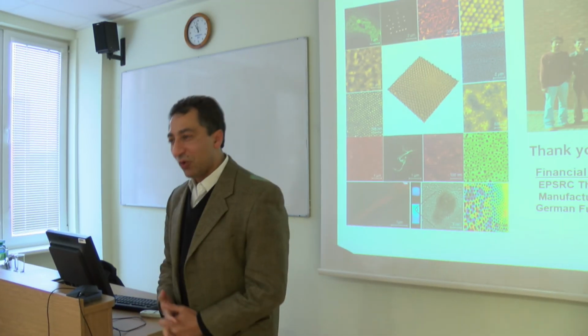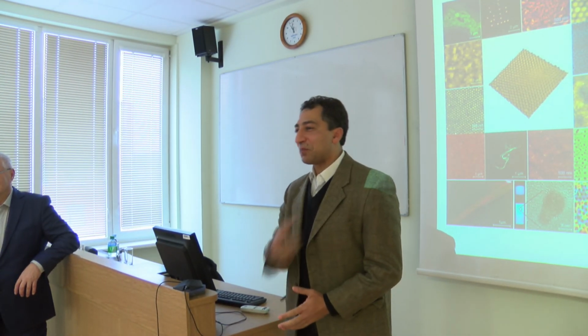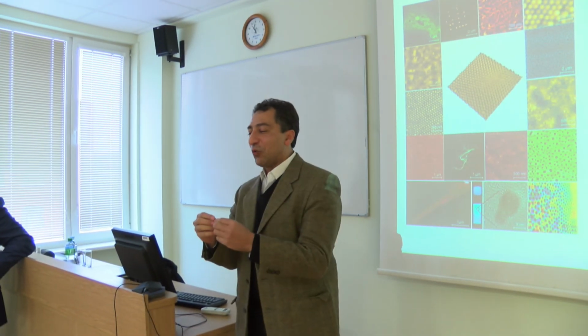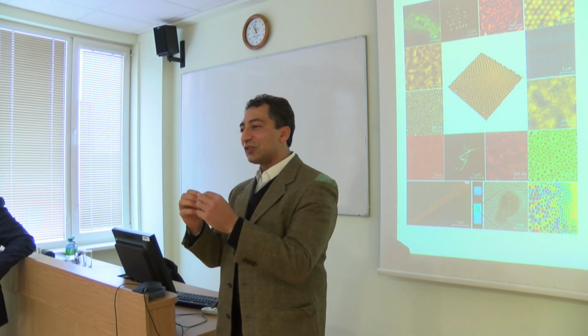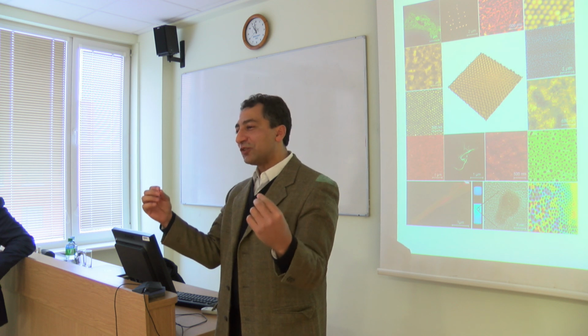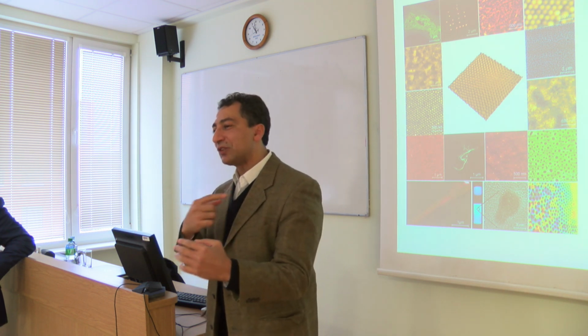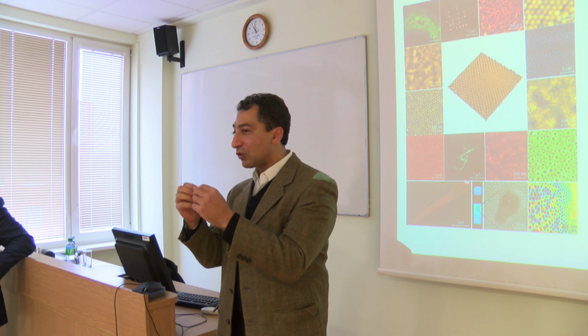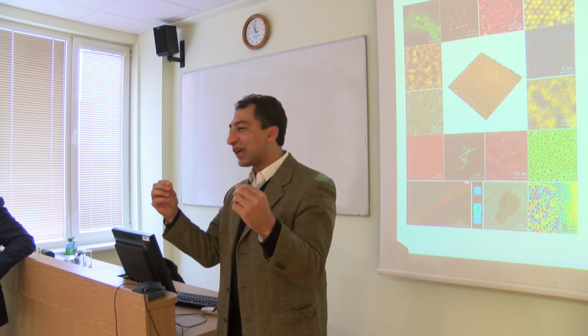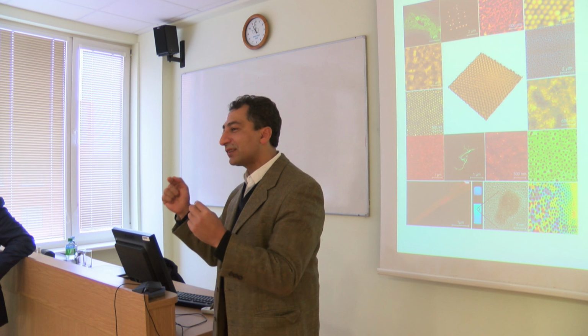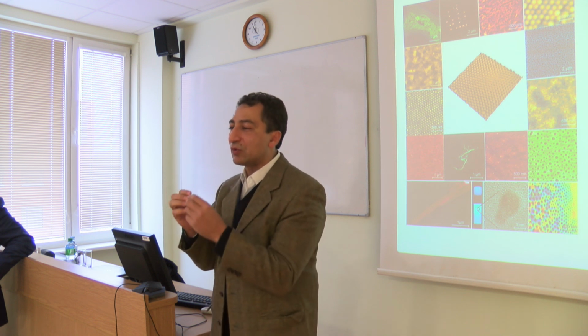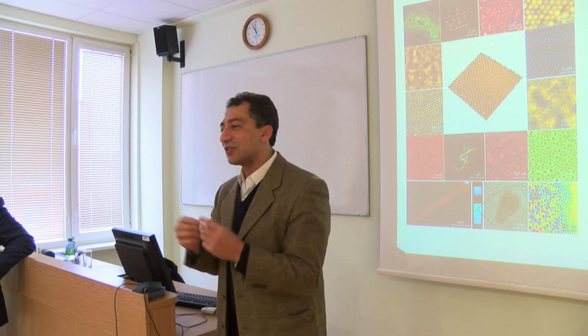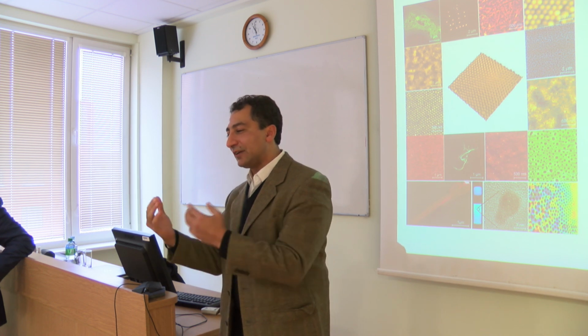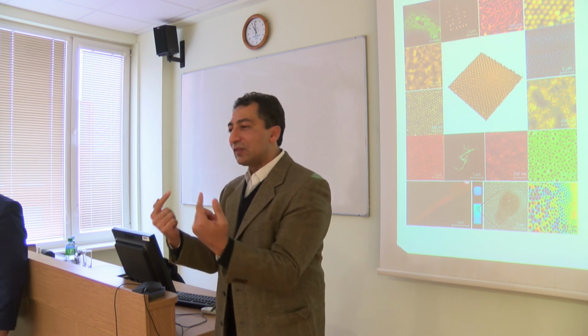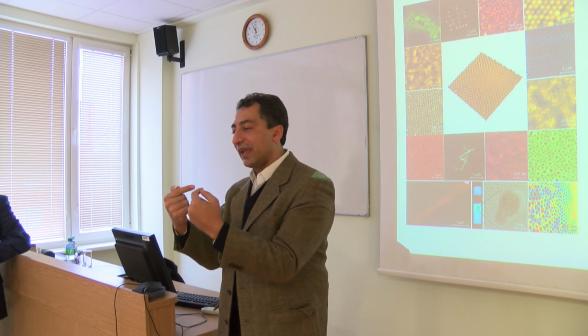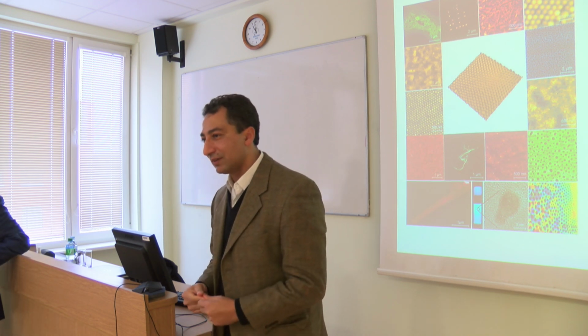Yes, thank you very much. It's really a very interesting question. Maybe I didn't explain quite well. 1D structure is quite interesting: you have a huge surface area. And what we try to do is make structure in structure. I put a big emphasis on making fiber, or 1D structure, but we were quite keen to align the gold nanoparticles inside the nanofiber in a discrete manner. In this case, you give more chance for electrons to hop or tunnel. And we found that well-defined distances can really induce these unique properties.